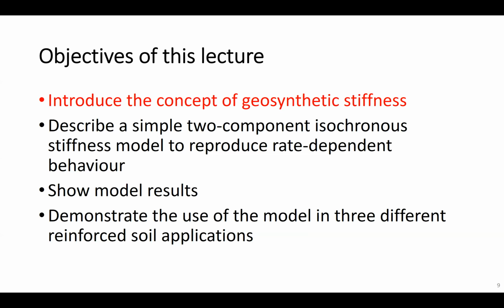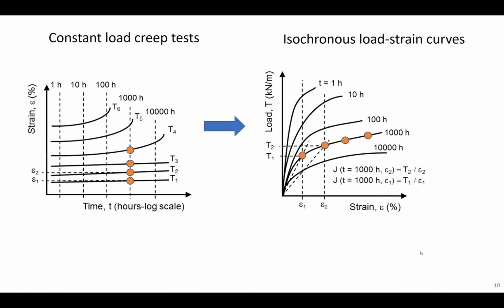So let's talk about geosynthetic stiffness. The slide on the left-hand side we've seen before. These are these constant load creep tests. And what we can do through these tests is take time slices, which you can see by the symbols. And using these values at the same time, we can construct isochronous load strain curves as shown on the right-hand figure in this slide.